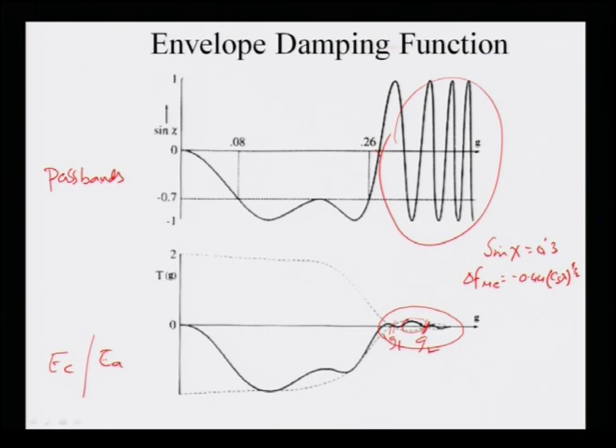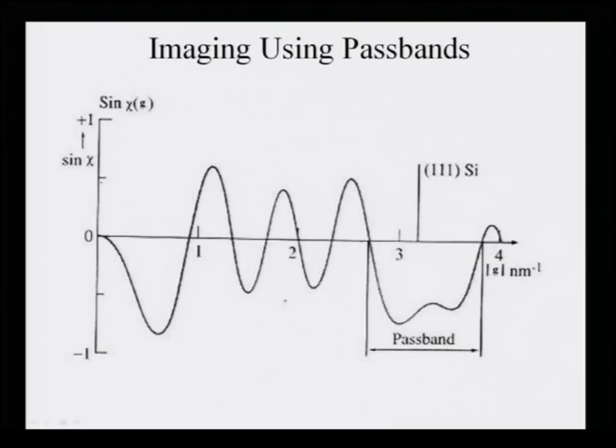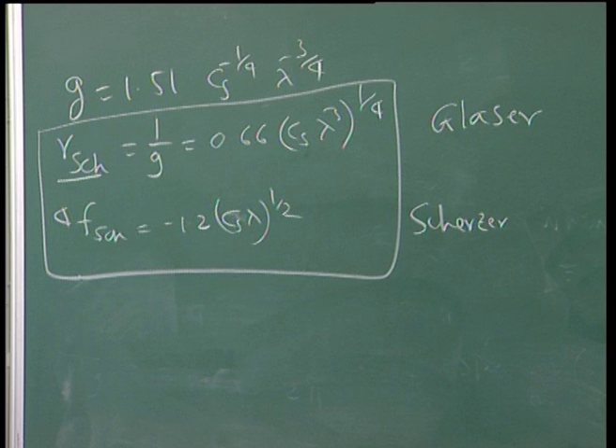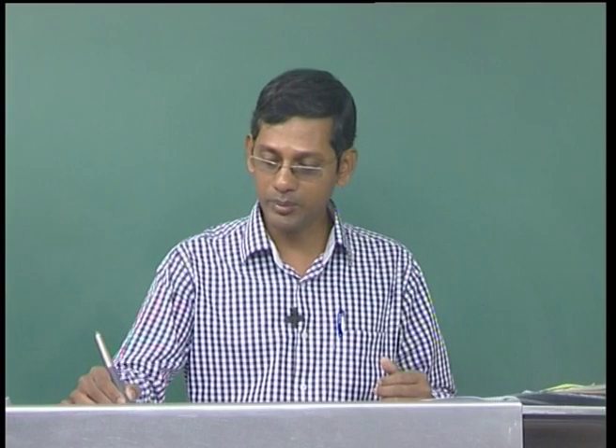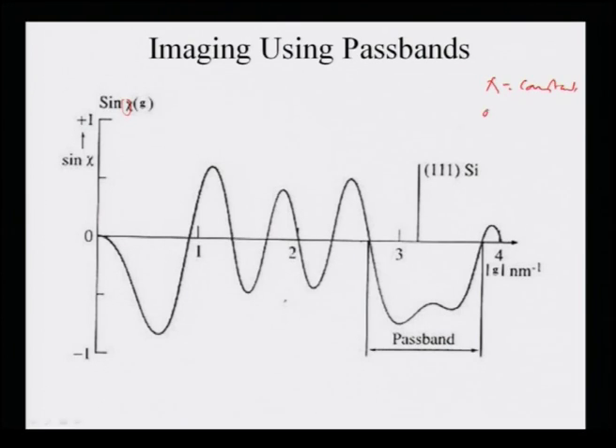Obviously, as you see from the next figure which I am showing here, very clearly you can see that this requires psi to be constant. Obviously the value of psi depends on g, and also depends on Cs and delta f. This requires psi to be constant, and also d psi to be constant and d psi by dg to be very small. One such example is shown here for silicon.